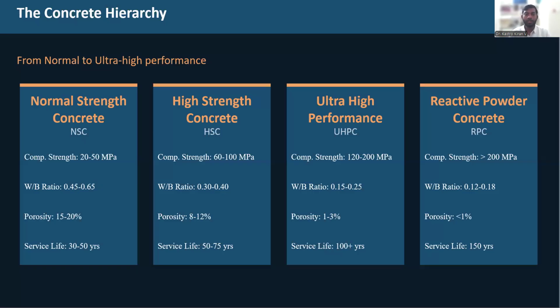To overcome the limitations of high strength concrete, especially in high rise structures or thin walled sections, we got an advanced one, which is ultra high performance concrete, where the strength varies widely between 120, 130 megapascals up to 200 megapascals, where we can drastically reduce the water binder ratio. At the same time, minimization of pores is also possible because of the material composition available in the UHPC. And again, we got a much higher grade of concrete, reactive powder concrete, where we can typically see strengths greater than or equal to 200, 220, 230, and even sometimes going up to 600 megapascals.